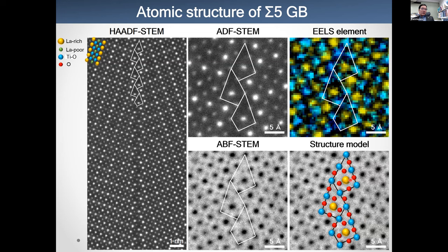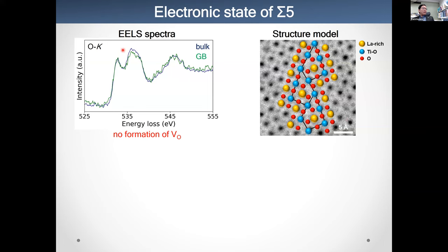Therefore, we can make the structure something like this. In the structure unit, one column of lanthanum is located, and at the corner, titanium is located here. So we can determine this very complicated structure at the atomic scale. Then we measure the EELS from these regions, the grain boundary region and the bulk region, the oxygen K edge. There is not so much difference. This means that there is no formation of oxygen vacancies at the grain boundaries.